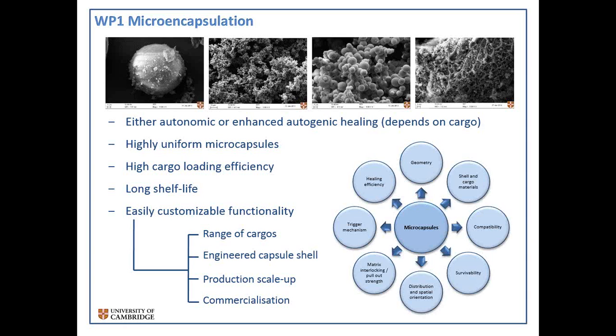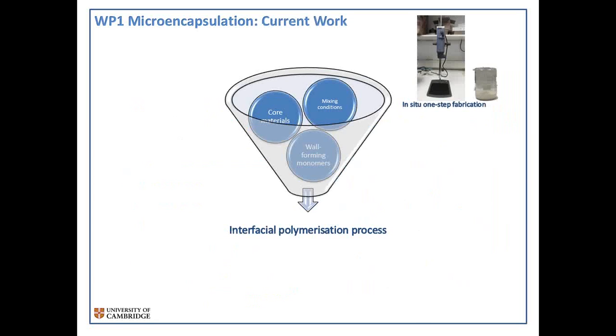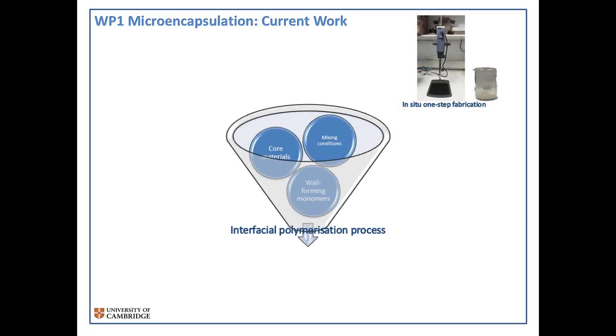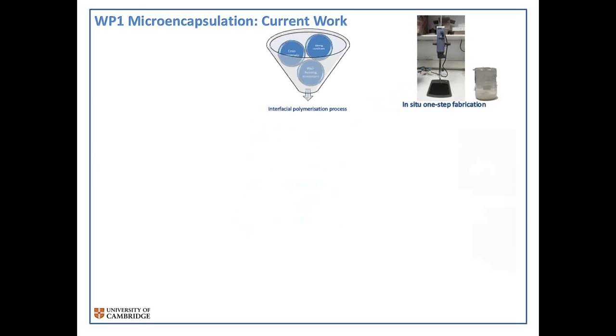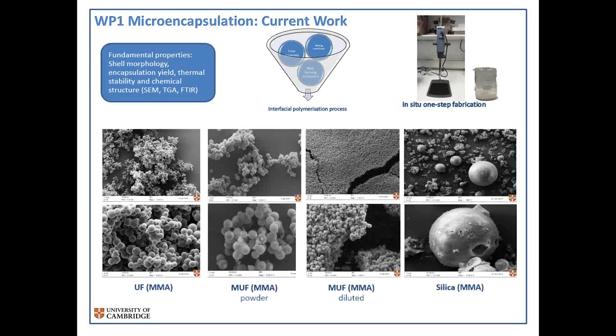So this is just a number of the considerations they're having to look at when creating these capsules. They have to have long shelf life, they have to be highly uniform, they need to be looking at the healing efficiency, the geometry, etc. So what they're doing at the moment is their current work. They're looking at different core materials, mixing conditions, wall forming monomers, etc., putting them through a polymerization process, and then they are investigating the optimum types of cargo and encapsulation materials to then put into concrete to allow for this healing mechanism. And again, this works at very small scales because these are only sort of 10 to 50 microns across, so they're quite small capsules.